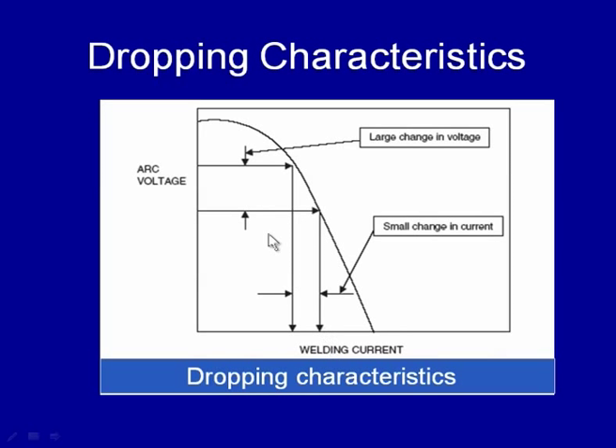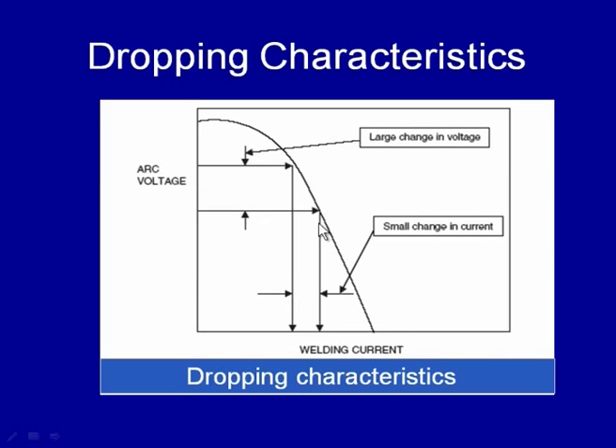So, an increase in arc voltage due to the increase of arc length will decrease the welding current by a small magnitude. The small change in current occurs while the change in voltage is significant. Indirectly, what we say is that if a large change in the arc voltage takes place due to variation in arc length, the change in current will be very small, which will not affect the heat generation to a greater extent, and that is why uniform heat generation helps in obtaining a smooth and uniform weld joint for better performance.